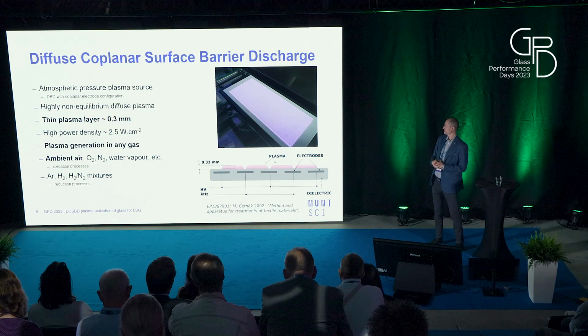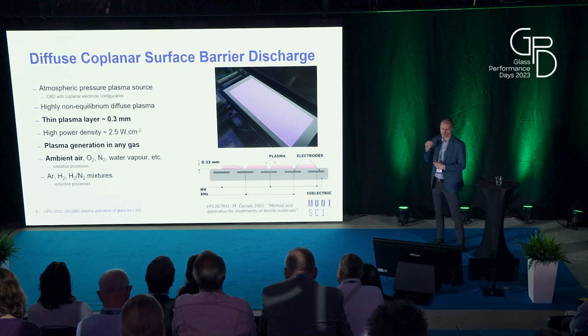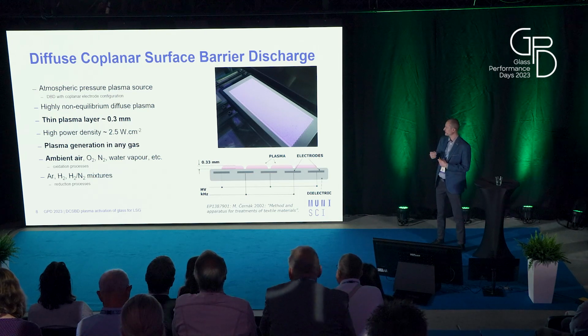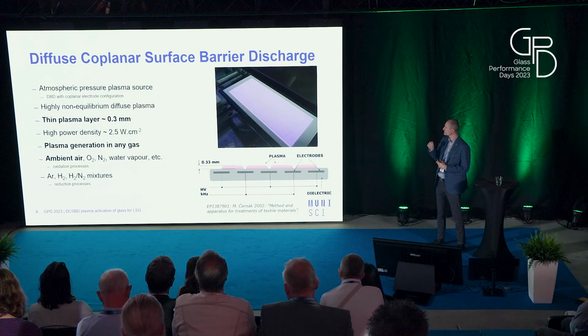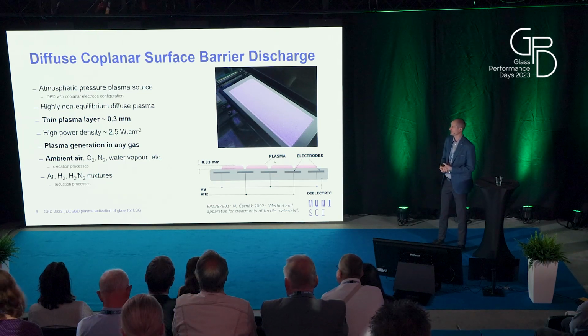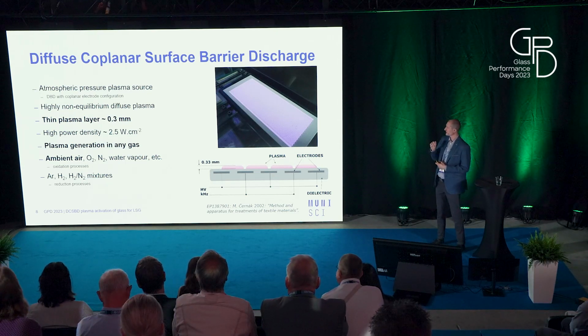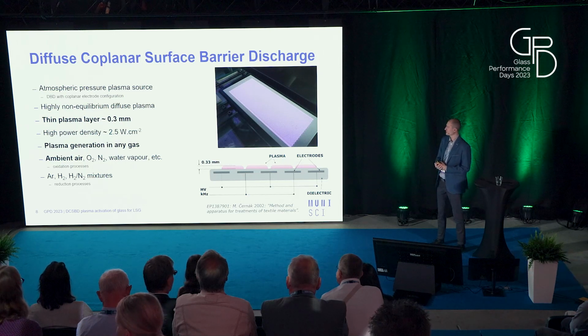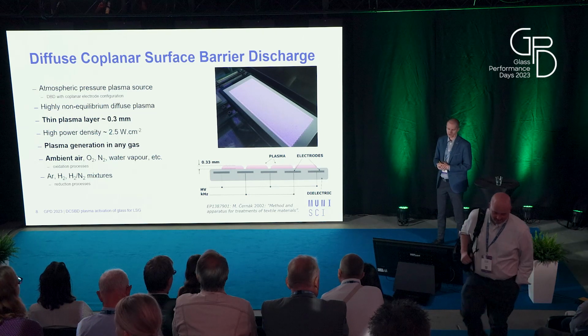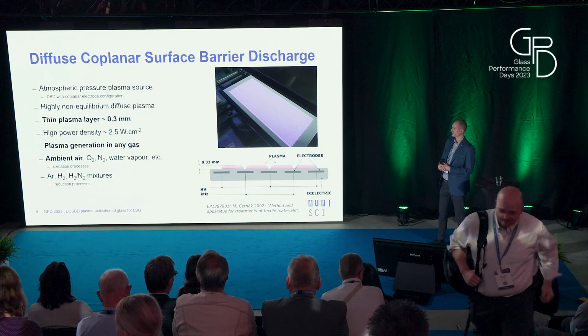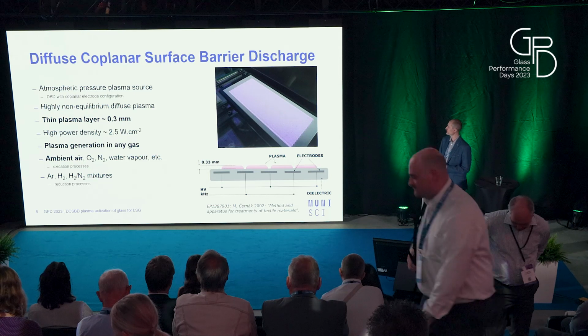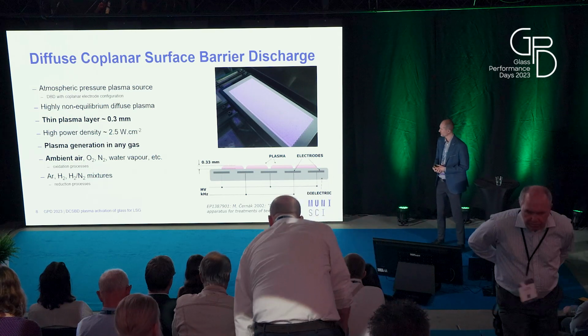The dimensions are roughly 8 by 20 centimeters, and the thickness of this plasma is only 0.3 millimeters. It's the effective thickness of the plasma, which can be used for treatment of the material. The thickness is not very large, but on the other hand, we can achieve very high power density and also very effective treatment of the material, especially for flat surfaces like float glass.